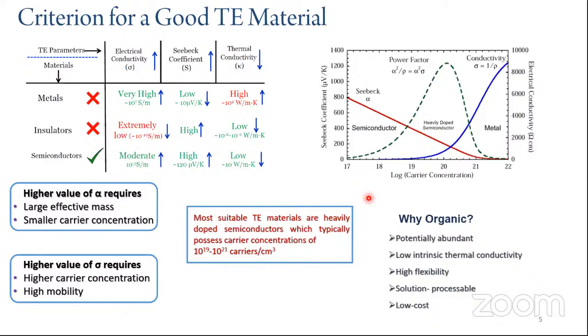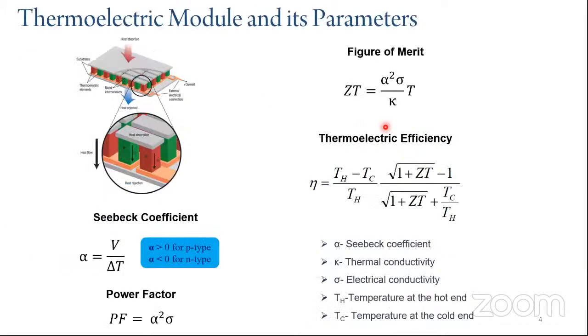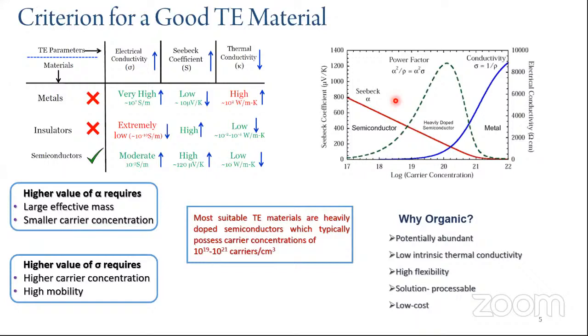And how to select a good thermoelectric material? In order to maximize the ZT, we have to minimize the thermal conductivity. So in that aspect, semiconductors are appropriate candidates, where we have a moderate electrical conductivity, which can be improved by heavy doping, a high Seebeck coefficient, and also a low thermal conductivity. So among the organic and the inorganic semiconductors, the reason for choosing organic semiconductors is their potential abundance, low intrinsic thermal conductivity, as mentioned before, high flexibility and solution processability, and low cost.